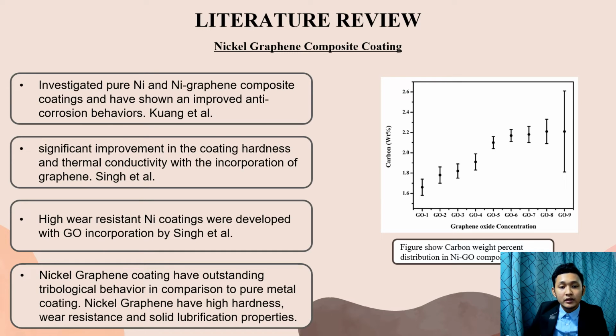Literature review: nickel graphene composite coating. Investigation of pure nickel and nickel graphene composite coating has shown improved anti-corrosion behavior by Kuang et al. Significant improvement in the coating hardness and thermal conductivity with the incorporation of graphene, by Singh et al. High wear resistant nickel coating was developed with graphene oxide incorporation by Singh et al. Nickel graphene coating has outstanding tribological behavior in comparison to pure metal coating. Nickel graphene has high hardness, wear resistance, and solid lubrication properties.